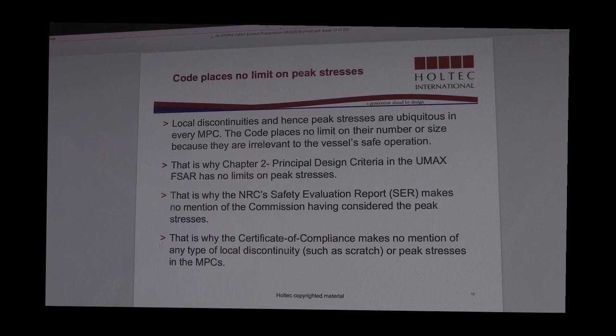I'll move to slide 12. And this just reiterates what I was just saying, that the local discontinuities are associated with peak stresses, and although peak stresses are common and present in the MPC, they pose no risk to the safety or structural design of the MPC for the reasons I just mentioned. And that is why, of course, in Chapter 2 of our FSAR, under principal design criteria, we do not place any limit on peak stresses with respect to the MPC canister. As I mentioned earlier, in Table 3.1.10 of the FSAR, fatigue is ruled out as a credible failure mechanism, as is brittle fracture. So there's no need to place any limit on peak stresses with respect to the MPC.